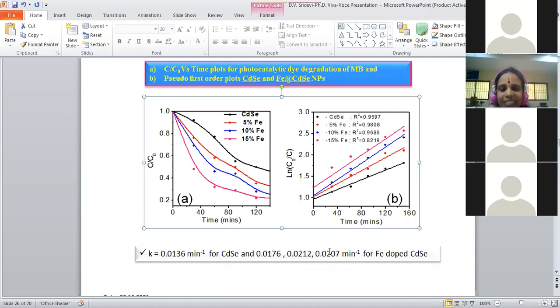Here also the R square value is decreased, sir, 0.8219. The R square value is around 0.9, which emphasizes that all the synthesized nanoparticles follow pseudo first order kinetics, sir. It may be in the range of 0.85 to 0.99.